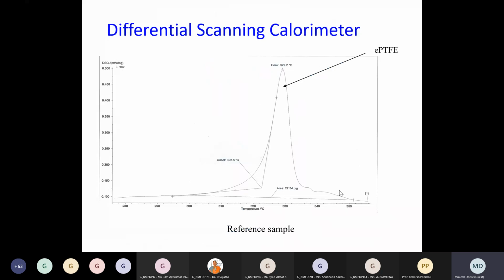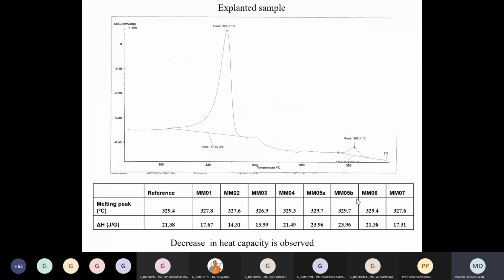Okay, so we first performed a study called differential scanning calorimetry. This gives you the heat properties of the polymer. So we wanted to compare the heat properties of the new polymer and an old polymer, and that tells you the crystallinity changes in the polymer as it is kept in the body for so many years. So for the explanted polymer, we looked at the heat capacity and compared it with the new, unexplanted polymer. The bottom table gives you that information.